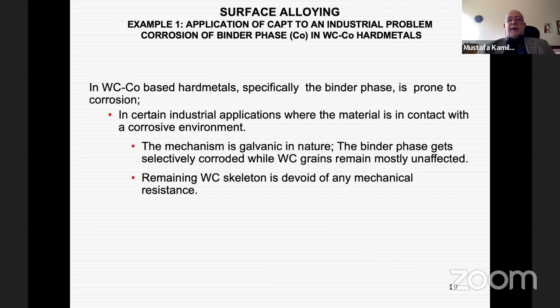Then we switched to another area. Like we said, we can also use this increased temperature behavior that can be obtained by the application of high voltage bias for surface alloying. So we said, we can heat our substrate to any temperature that we require. We can coat any material that is available as a cathode onto the surface of our material. So why don't we coat and heat the material so as to induce a diffusion between the substrate and the coating material? So we started with an industrial problem.